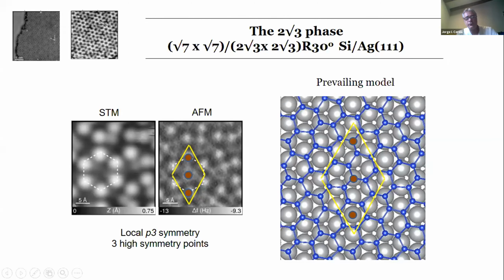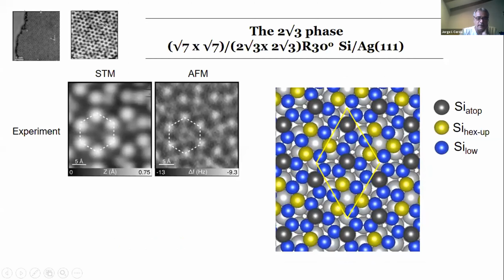Because, for instance, basically you need to place the silicene and start placing the silicon atoms so that they respect this P3 symmetry. So the silicon atoms should sit on top sites or FCC or HCP sites. I just showed you this case, which is the prevailing model. We made a relaxation for that one. It's again a good silicene sheet covering the entire surface. And now we have three types of silicon atoms. Ones that are sitting on the top site, and then these are the type of atoms which are making these hexagons around the top site, and they are buckled. So we have three silicons that are standing up, and three others that are standing lower, similar to what we had in the previous phase in the 4x4.